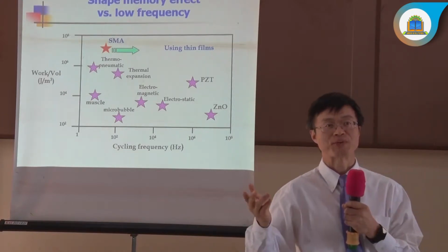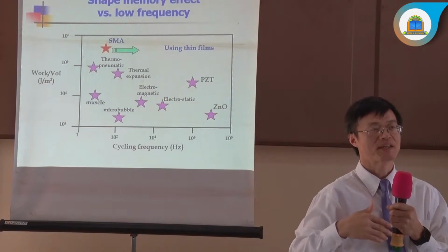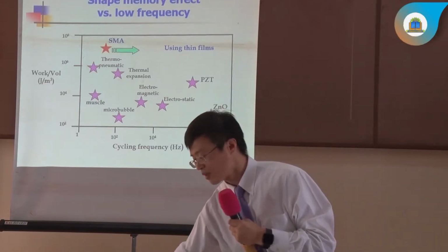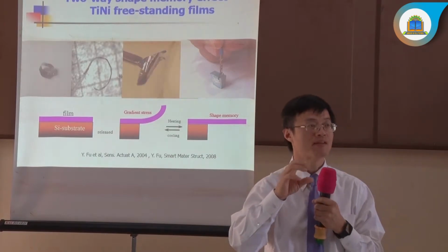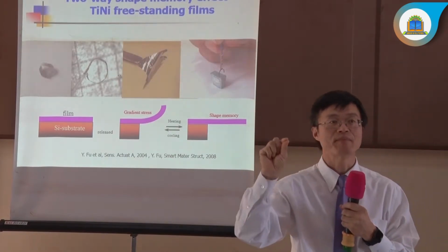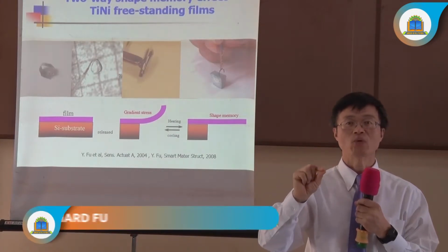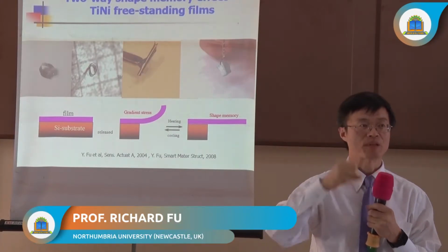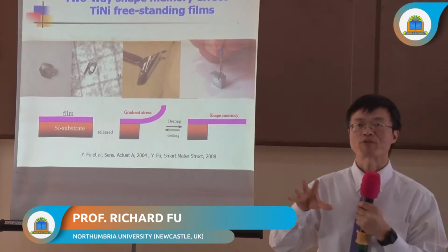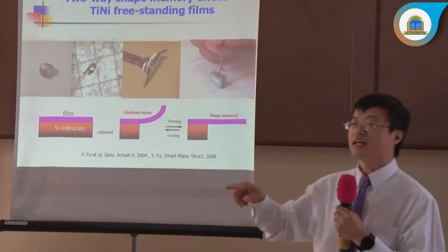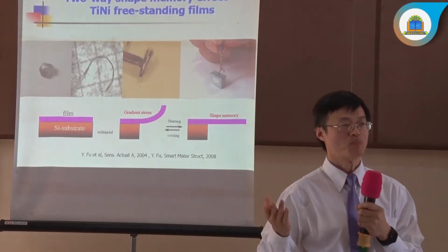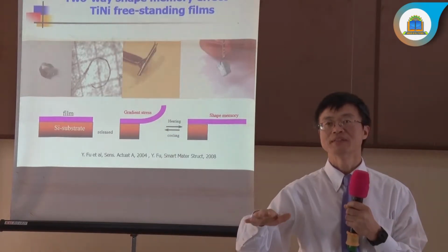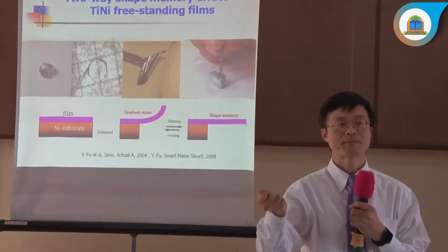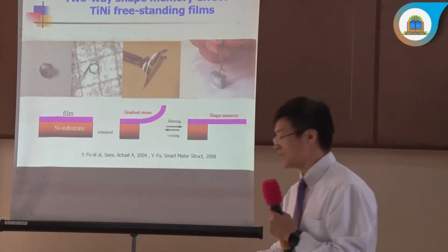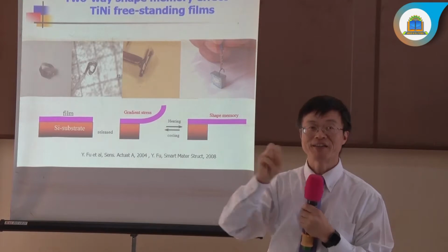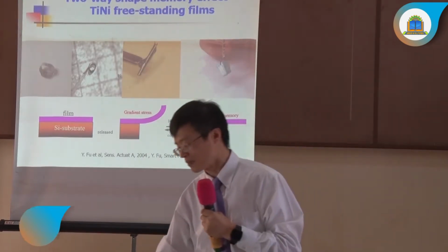So how can we increase the frequency? We operate very, very fast. The way we were doing is that we can use thin film, make the thin film deposition, make a very, very thin material, and then this material will be easily heated up, cooling down. So the material will be faster and more powerful to actuate. So this material is actually like metal. It's nickel titanium. And like metal, you can deposit the metal. The metal is very ductile. You can peel off from substrate and then make it into structure, right? And then, so this is just a freestanding film. We can easily use heating, cooling, and activation, right?